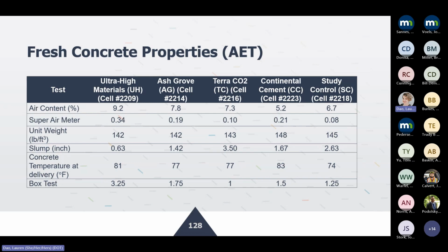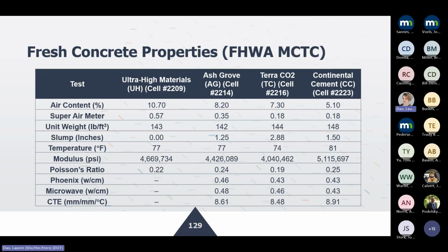And I don't even know if they could do the testing properly with some of those initial mixtures, because the material that they got to cast, do the fresh concrete testing, and maybe even cast some of the concrete cylinders and the beams was less than ideal for that particular material. But overall, properties were very similar to what you would expect from your typical conventional paving mixture. And this was the testing performed by the Mobile Concrete Center.